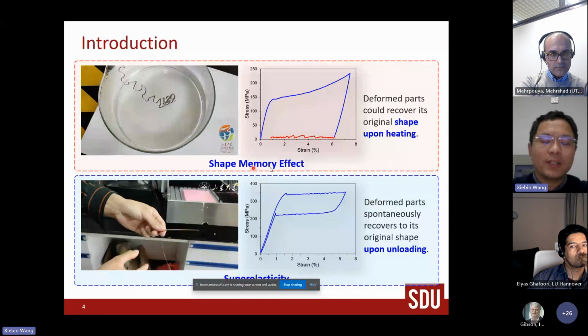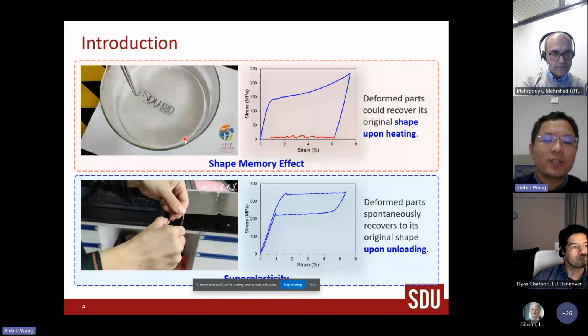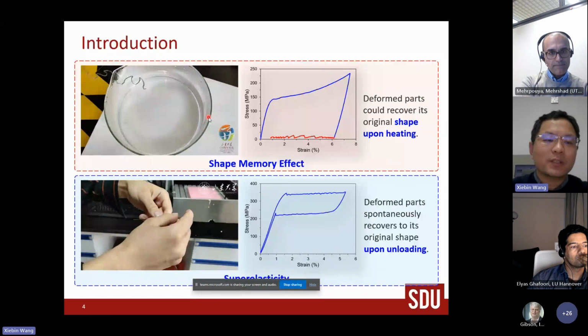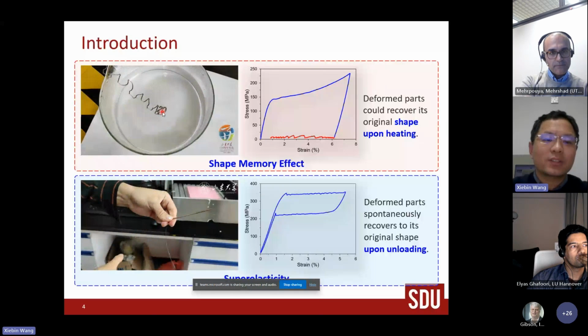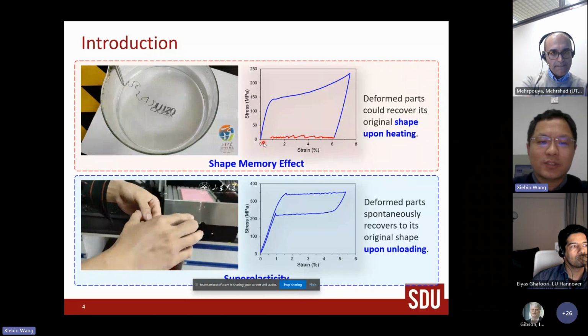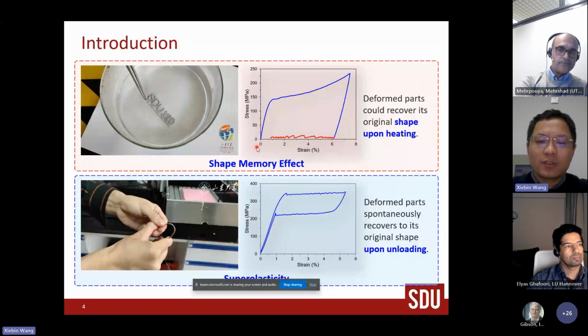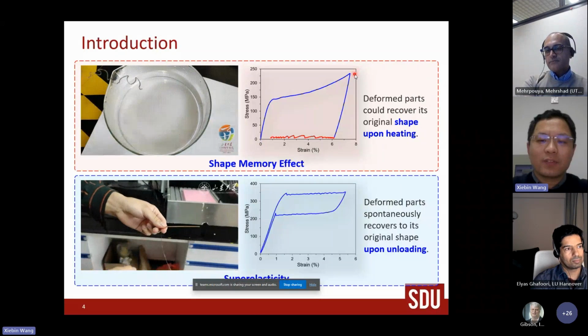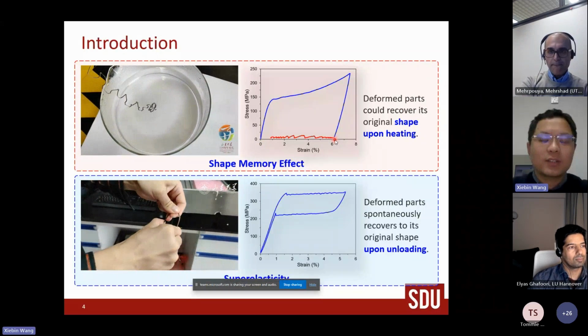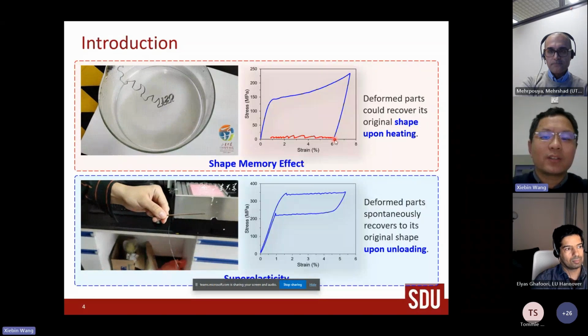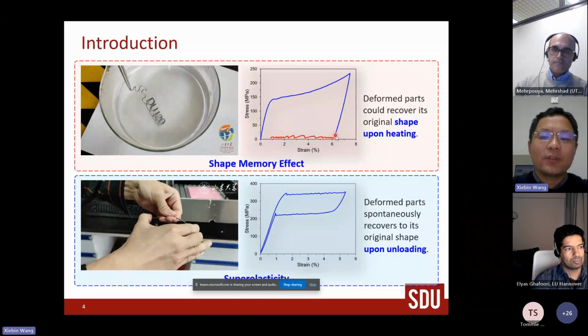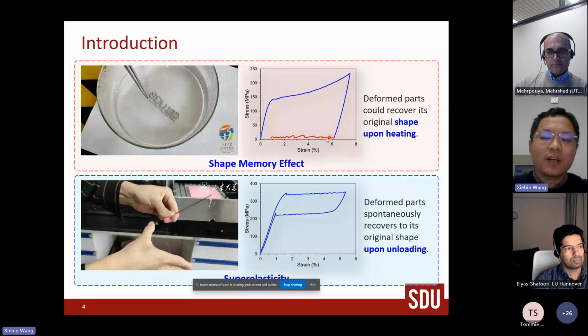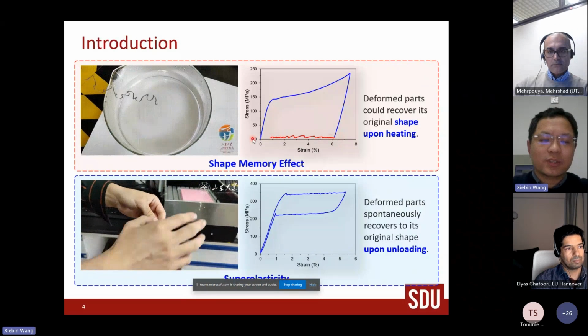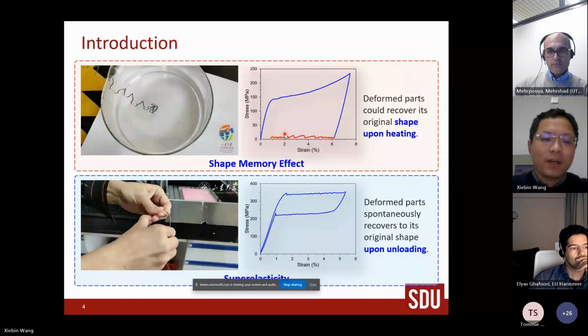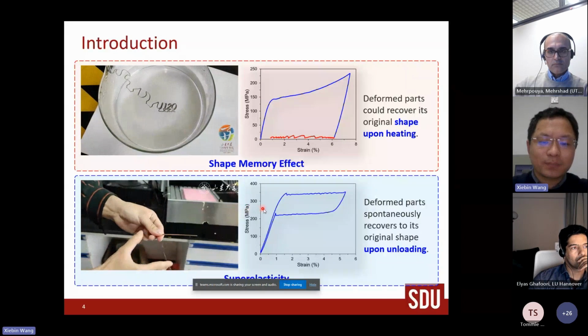For shape memory effect, it means if you deform this material and then heat it up, so increase the temperature, the deformed sample will recover back to its original shape. If you look at the stress strain curve, during loading, the material is deformed. After unloading, no recovery, so the sample remains in the deformed state. But if you increase the temperature, the red curve, then it will recover to its original shape. It's called shape memory effect.